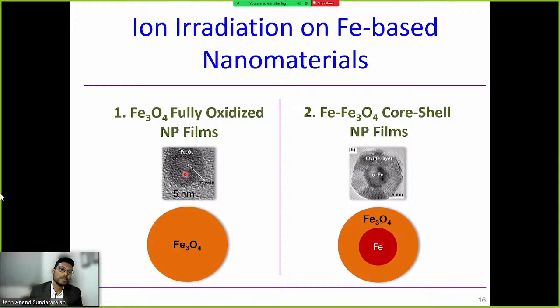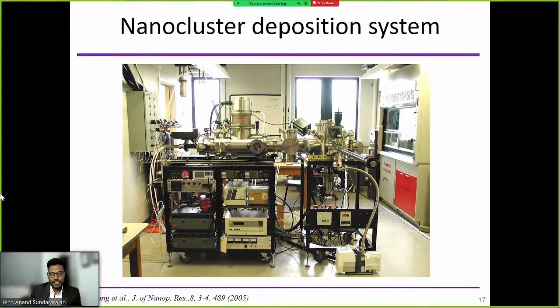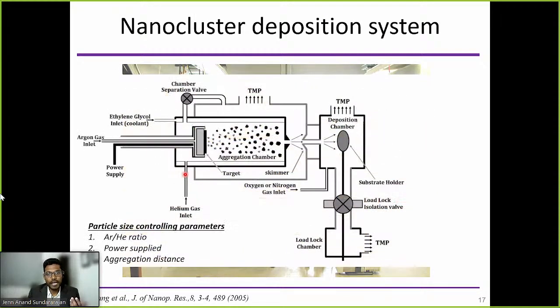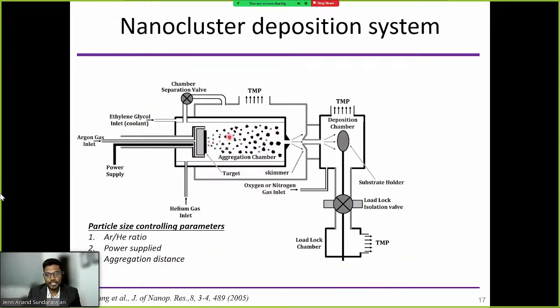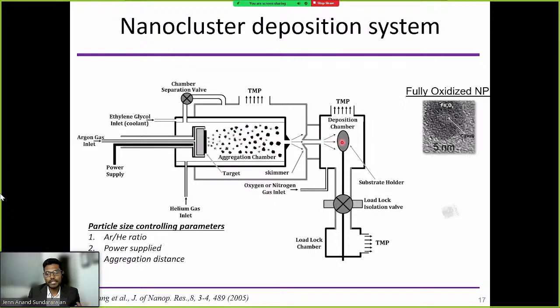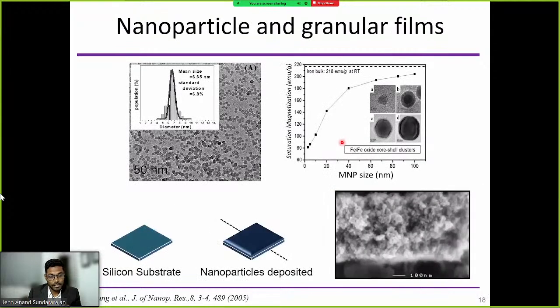And then the nanocluster deposition system. This is our deposition system that we use to create particles. Basically, we sputter these particles, aggregate them in the chamber, and allow them to deposit on the substrate, and then it forms the fully oxidized nanoparticles. This is a picture showing how the particles look. These are monodispersed particles, with the size very uniformly distributed. You can see the bell curve here, a narrow distribution, pretty much all having the same particle size. And this is how it looks in cross section on the silicon substrate with deposited particles; you cut it, and this is how it looks on the right side.